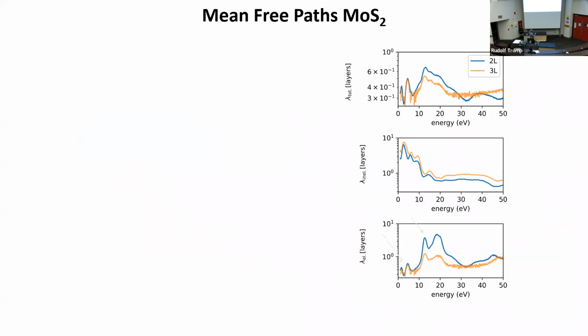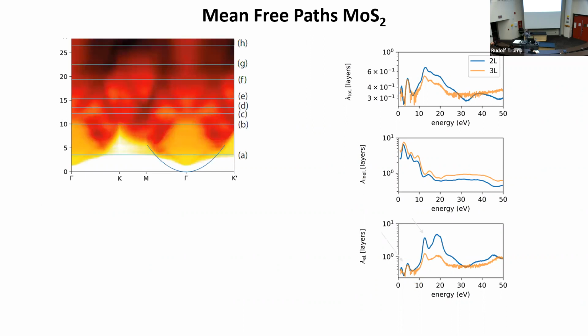We can do this for molybdenum sulfide. I will just show the elastic mean free path, very small, 1/10 of a layer, right? The electrons simply do not want to enter the solid. Why is that? We can look at our angle resolved reflectivity. What we see is this huge band gap here, right? We have this huge band gap which corresponds to the electrons not being able to enter the solid.